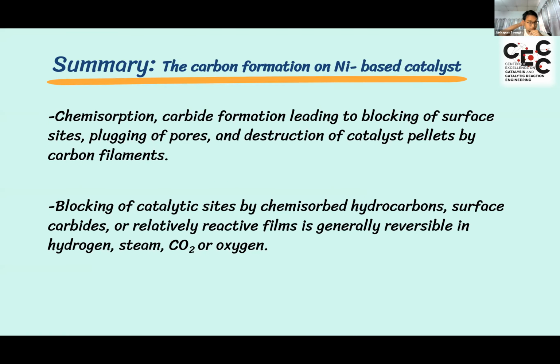It is the summary of the carbon formation on nickel-based catalyst. The deactivation of supported nickel metal by carbon may occur by chemisorption, carbide formation, or physically owing to blocking of surface sites, blocking of pores, and destruction of catalyst pellets by carbon filament. By the way, blocking of catalytic sites by chemisorbed hydrocarbon, surface carbide, or relatively reactive films is generally reversible in hydrogen, steam, CO2, or oxygen.